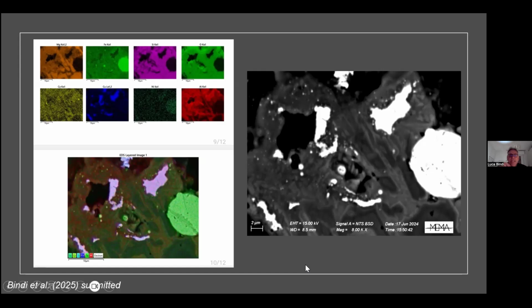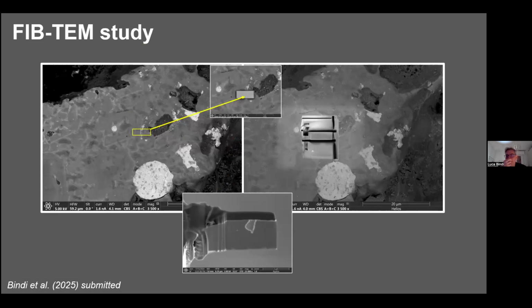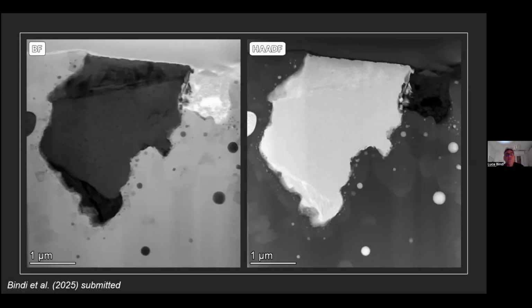So we decided to study these copper aluminum alloys by the combination of focused ion beam and transmission electron microscopy. Look at this. We selected actually two lamellae, but I want to show you the results of one of these lamellae because they are actually impressive. Because this is the FIB lamella. Look at the bright and dark field image in the transmission electron microscopy, and you will see the chemical maps in just a few seconds. But I want to show you the homogeneous region here, which turned out to be a new copper aluminum alloy never described in Khatyrka or in the other micrometeorites. So it is the first time.